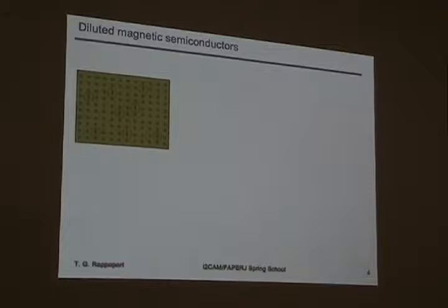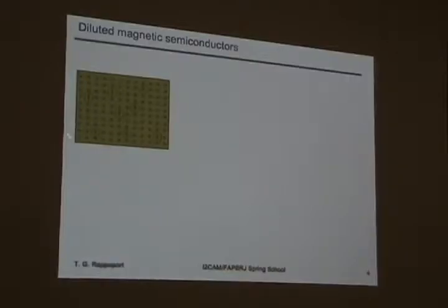In a normal metal, we know that carriers play an important role in the exchange interaction between very localized spins to produce magnetism. But in a semiconductor, in principle, we don't have free carriers, only if we dope this semiconductor, and we don't have localized spins. So if we want to have a magnetic semiconductor, we must introduce this magnetic moment. For example, doping this semiconductor with manganese.